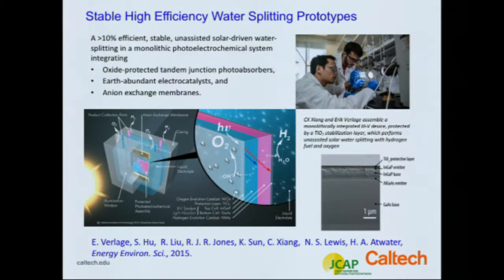So that culminated in a number of prototype devices, and these are some of the JCAP researchers that were instrumental in building one of the first stable, efficient devices—by efficient we mean devices with efficiencies over 10%—water splitting efficiency, that's photons in, molecular hydrogen out. They feature oxides, doped titanium oxide layers that protect the intrinsically unstable 3-5 semiconductor photoelectrodes. They have earth-abundant electrocatalysts, and they use anion exchange membranes to pass hydroxyl across from the cathode to the anode side.